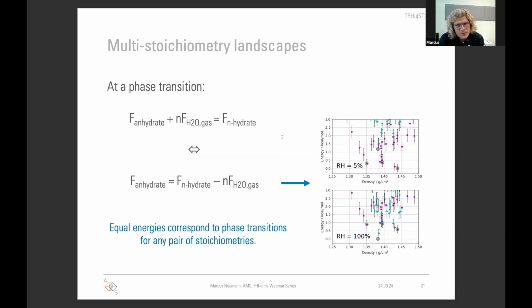And then to compare multiple stoichiometries, it's more convenient to put the gas phase term onto the right side. So we actually subtract the gas phase free energy from the hydrate free energy. And then we can compare every hydrate to the anhydrate, so we can also compare the hydrates among themselves. And in these plots, so these crystal energy landscapes with error bars for different hydration states that I will show you, things which have the same energy, so the same location on the y-axis, are structures of equal free energy with a phase transition condition.